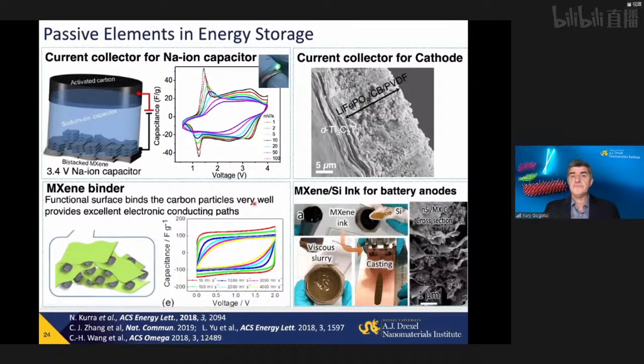What is also important, you can use MXenes as active materials in supercapacitors, batteries, and also hybrid devices. But a lot of improvement can be achieved by also using them as passive materials, or both passive and active material, using them as current collectors, using them in a binder, for example, for silicon, tin, or other materials with large volume expansion, poor conductivity, but high capacity, large energy storage ability.